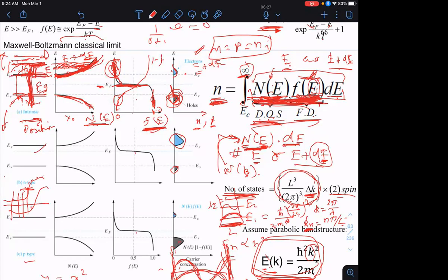There's no electric field, therefore there's no variation of the electrostatic potential, and you get the same electron concentration everywhere. So once again, I choose any position. It doesn't matter, if it's a homogeneous system, it'll be the same everywhere. And at that position, I figure out how many allowed states there are as a function of energy. I plot that on the second column. Then for each of those allowed states, I find the average occupancy. That's my F of E, plotted as a function of energy.